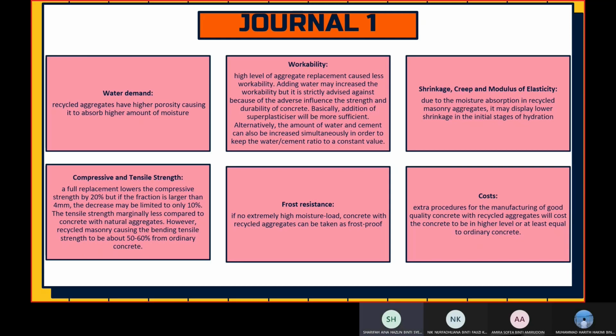The next property is compressive and tensile strength. A full replacement lowers the compressive strength by 20%, but if the fraction is larger than 4 mm, the decrease may be limited to only 10%. The tensile strength is marginally less compared to concrete with natural aggregates. However, recycled masonry causes the bending tensile strength to be about 50 to 60% of ordinary concrete.